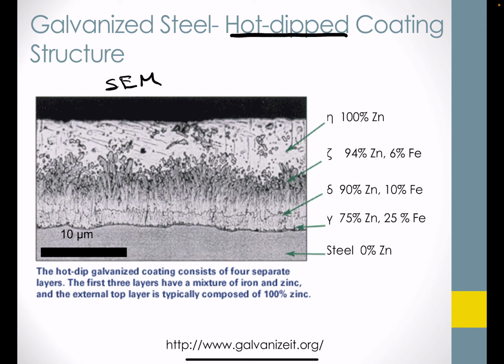You can see here that in fact there is a very much a layered structure, so that the steel is found below. Okay, so this was the surface of the structure down below. Notice that it has 0% zinc in it. And then as we move up towards the surface of the ultimate structure, we start to see the zinc presenting itself, and we see different phases. Here we have a gamma phase, a delta phase, a zeta phase, and an eta phase that take us all the way through to the pure zinc at the top. So the eta phase is pure zinc. So these roughly 4 layers are shown here, and of course the pure steel is extending down below.